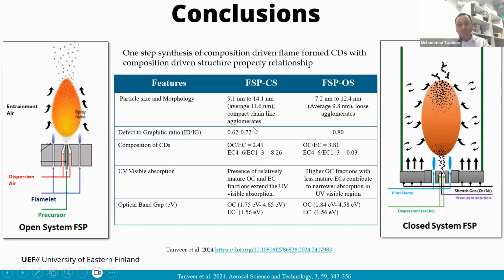And also, as far as the composition is concerned, the EC4 to EC6 to EC1 to EC3 fraction is quite higher in the case of the closed system. So this shows that we have more graphitic carbon in the closed system. So here we can use our graphitic and organic carbon to tune the properties of our carbon nanostructures. Also, OC and EC, both these features will contribute to the optical features of these carbon nanostructures.